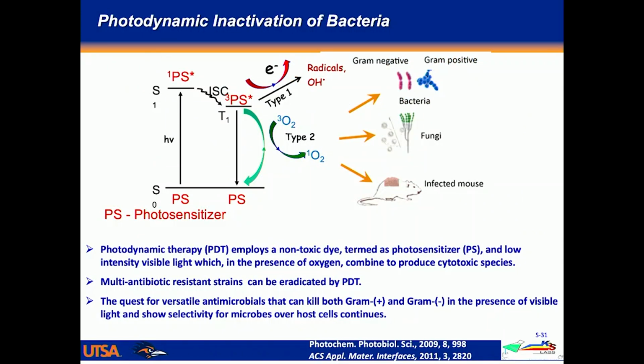So these polyelectrolytes absorb light, and that creates excited states. I've been talking about fluorescence from an excited state. It turns out there's another type of excited state that can be produced on excitation of these materials, and that's a triplet excited state. And triplet excited states are well known to interact with oxygen in different ways to generate either radical type species through what's called a type 1 sensitization mechanism, or generate reactive form of oxygen called singlet oxygen, and that's called a type 2 photosensitization mechanism. Both of these forms of reactive oxygen, radical oxygen or singlet oxygen, are really toxic to microbes and mammalian cells, and so they're quite effective at essentially cytotoxicity.